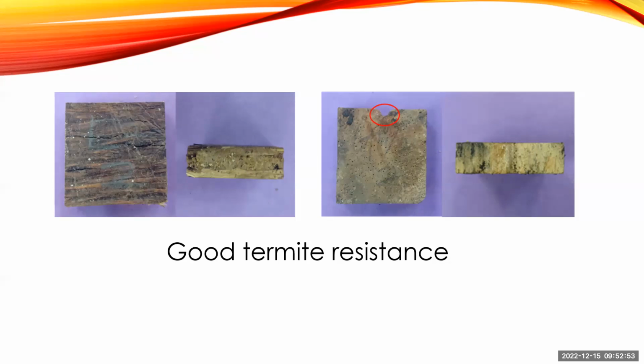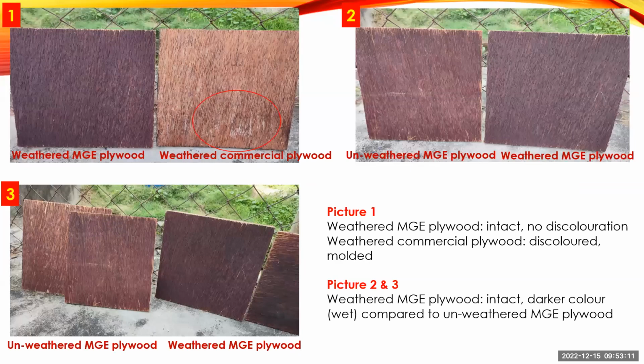This is the controlled rubber wood sample; we can see some minor damage by the termites. So compared with the resin treated plywood, which displays quite good termite resistance, and also very good weather resistance.